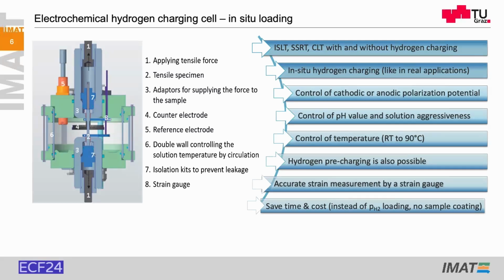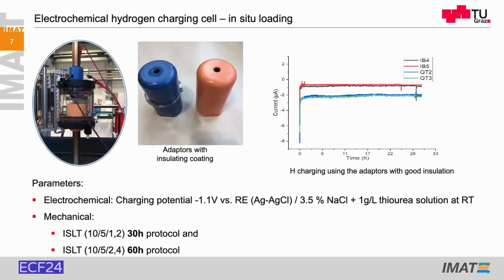Here are some of the advantages we evaluated. Of high importance is that there's very good insulation of the tensile specimen in the cell, and the core elements are here for sure. The adapters must have quite a stable coating, which is resistant to the electrolyte, to acidic or basic substances. And here we proved that we get quite a stable signal. We chose minus 1.1 volts against the silver chloride reference electrode. And as I told, we used 30 and 60 hours testing protocol.